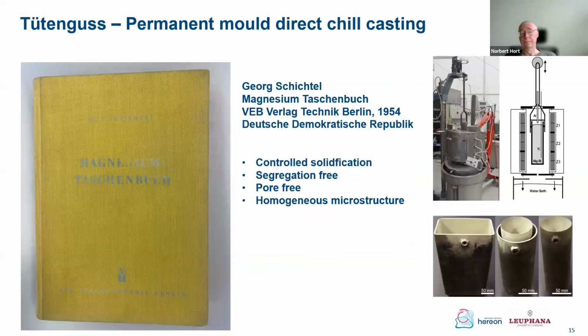When we look for the casting process, sometimes it might be of interest to look to an ancient book, perhaps. This is from the German Democratic Republic. Mr. Schichtel, he brought this magnesium pocketbook out in 1954, and we found a process that is called Tütenguss. I don't know an English word for that, so I created that on my own, called it permanent mold direct chill casting. That's more or less the same process that was called direct chill casting before, and it's pretty interesting because you have some first, where you put in the specimen, you hold it for some time, then you dip it down in the water bath.